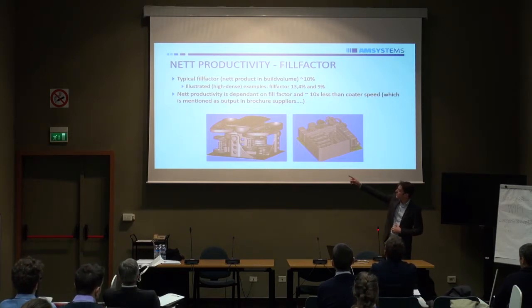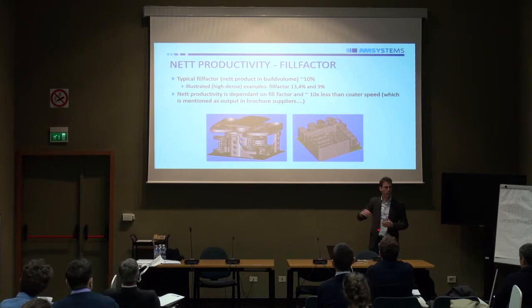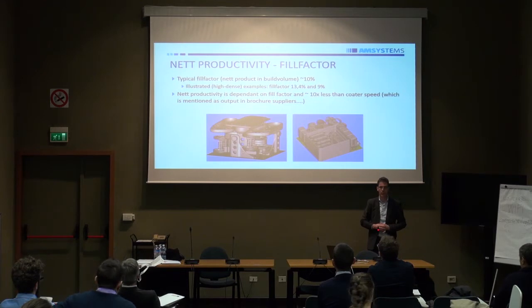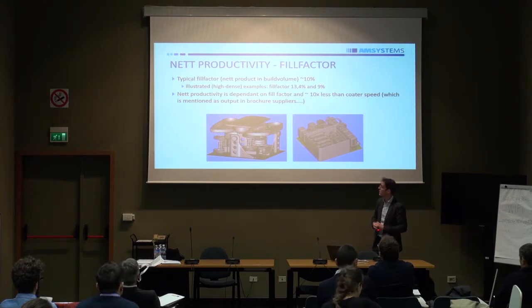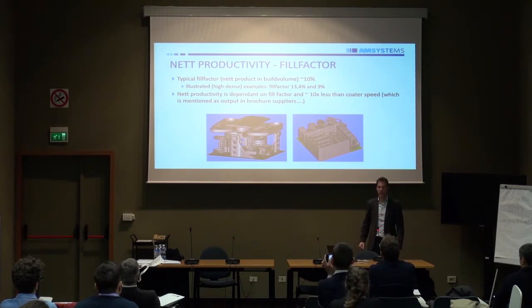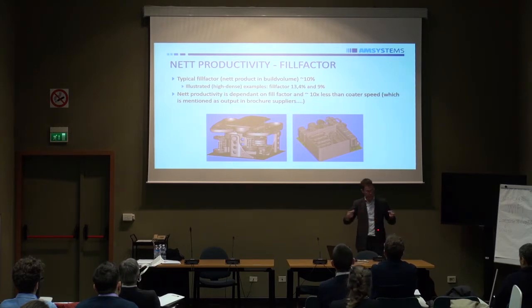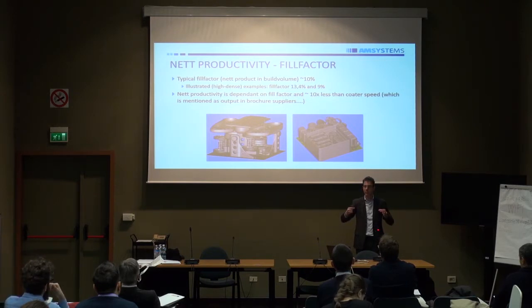What you see on the left here is a typical build box. They prepare it to stuff as many products in a limited volume as possible, because then you utilize the process as good as possible. But still, when you do that and somebody is really putting a lot of effort in it, the typical fill ratio is between 5 and 10%. So 95 or 90% of the powder doesn't have to be sintered. And with a line array, it's just as easy to sinter all the material as sinter only 5 or 10%. But for the CO2 laser, it makes a lot of difference.